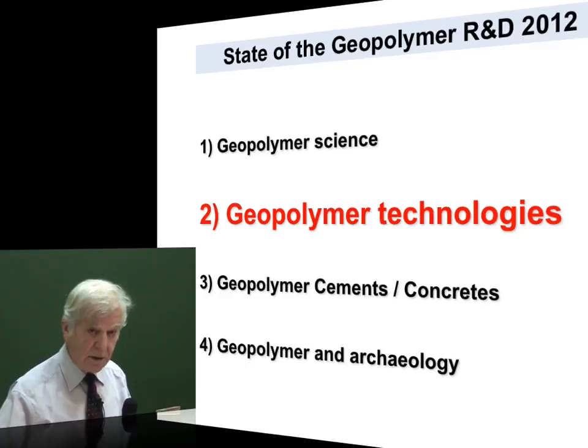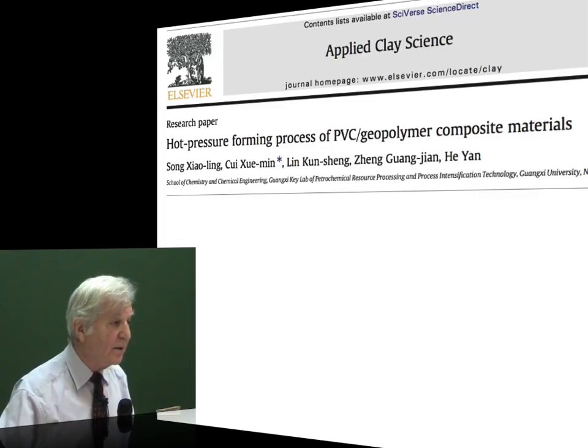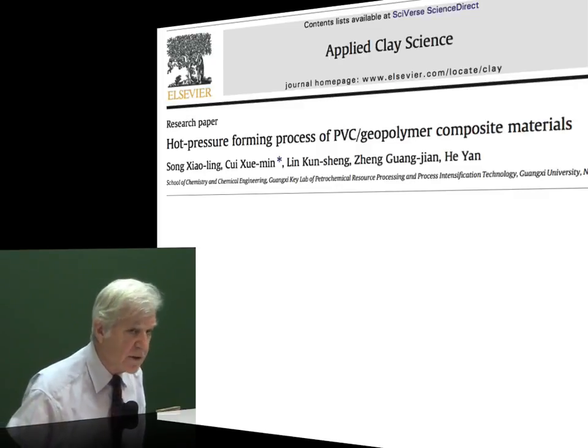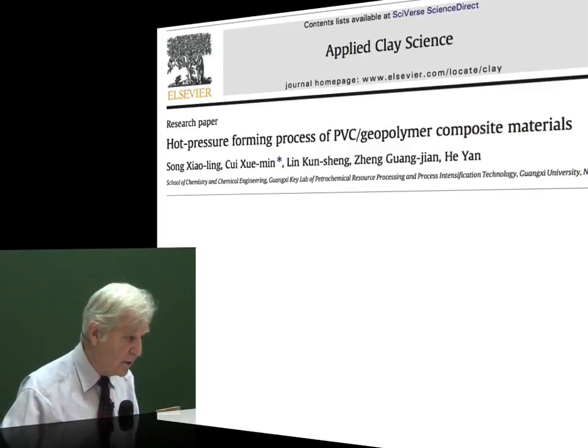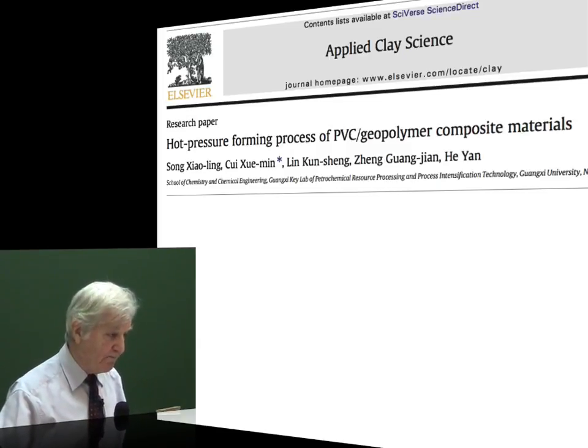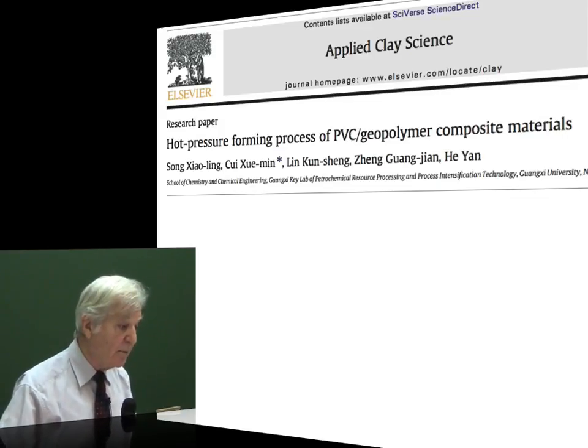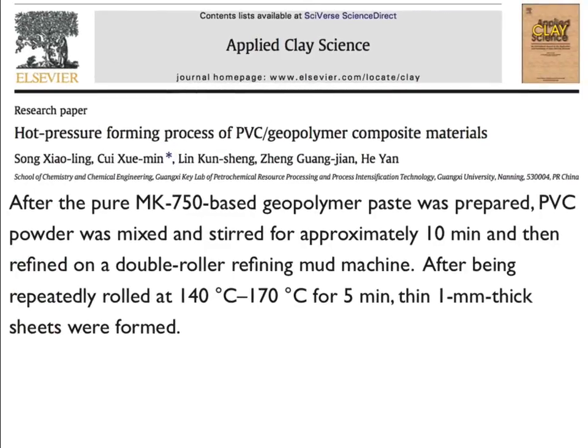But in fact, with geopolymer technology, we still remain with mixing organic with geopolymer, but here it is a totally different processing system. There's a Chinese group at Guangxi University, hot pressing forming process of PVC geopolymer composite materials. They first prepare MK750 based geopolymer paste, and then they add the PVC powder, they stir, refined on double roller, so they used their double roller equipment. After being repeatedly rolled at 140 degrees C, 170 degrees C for 5 minutes, thin 1 millimeter thick sheets were formed. So they process in a dry system.